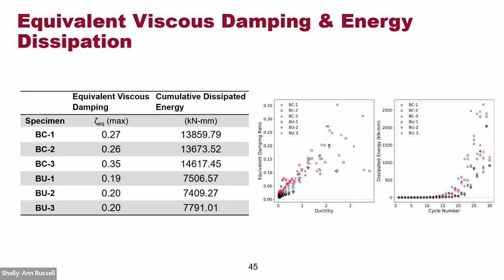When the buckling happens after cycle 12, you can see the energy dissipation starting to drop. Also, during the test, I observed that after cycle 12 there was permanent buckling at the web of the sections. And you can see just the small lips can change energy dissipation a lot.